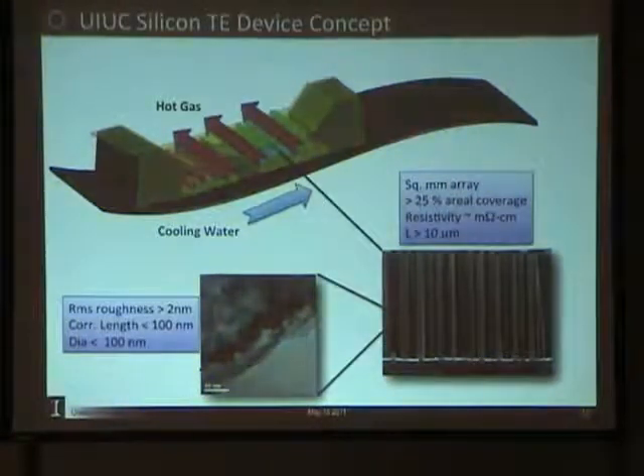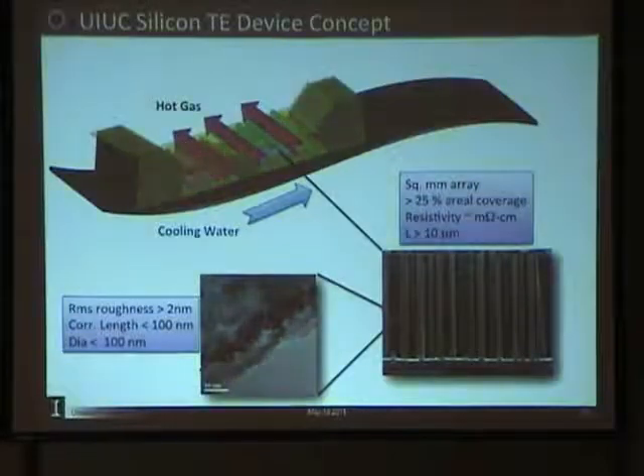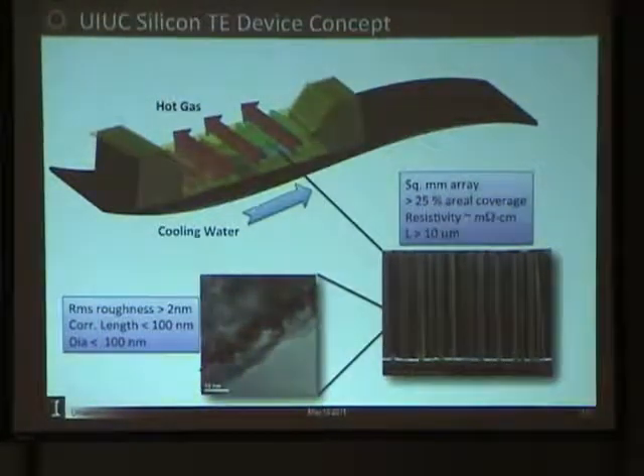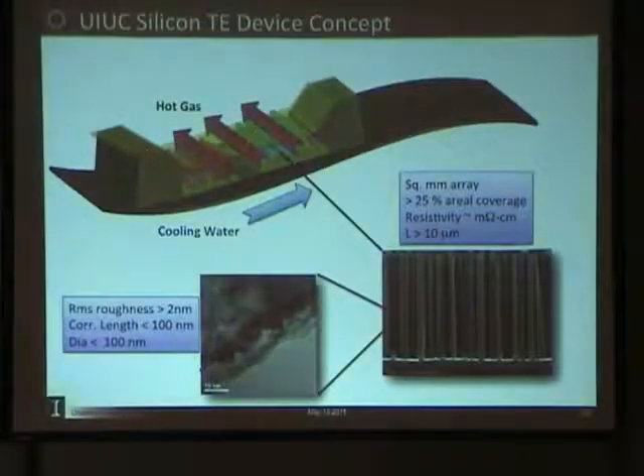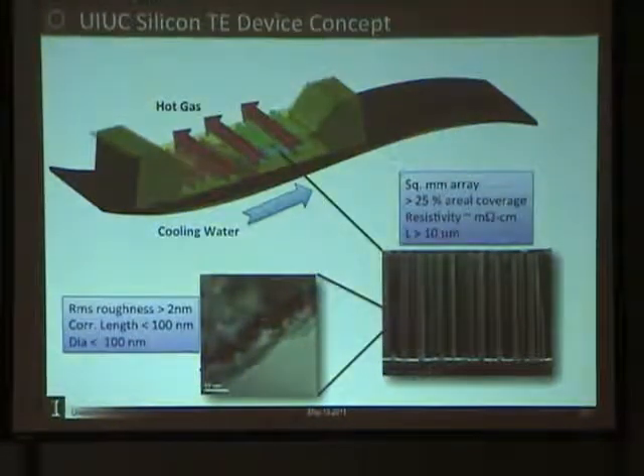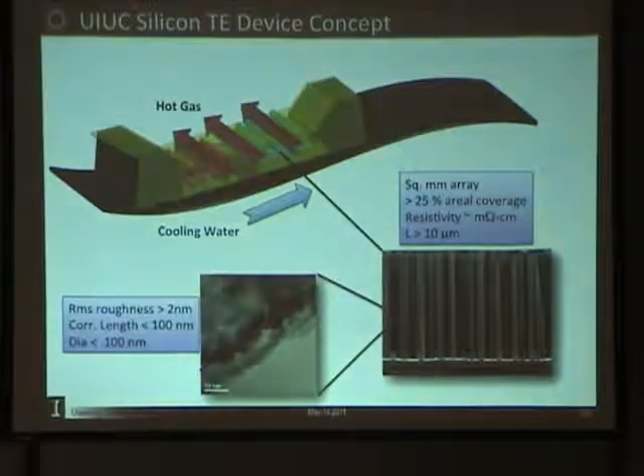We lead a large effort on campus, spread across about five faculty in electrical engineering and materials science, working to build a thermoelectric generator composed of silicon nanowires. We have P-type wire arrays and N-type wire arrays — whole arrays of wires because one wire is not very efficient. So we want something on the scale of millimeters containing hundreds of thousands of wires. There's the science part, and then there's the hardcore engineering part that comes in: making contacts, which are all very lossy mechanisms, so even though one wire taken together is very nice, making a device out of it requires working on other problems.